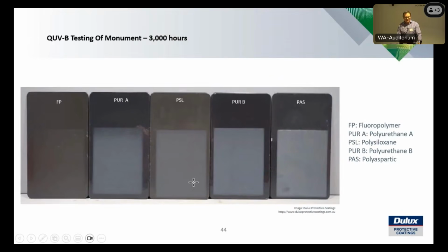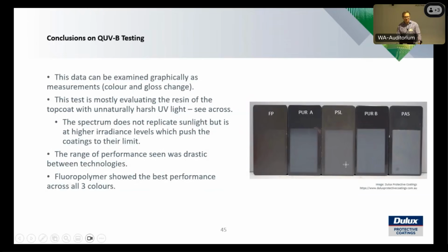And at 3,000 hours, the Colorbond Monument looks like Colorbond off-white in some instances there. And the fluoropolymer, there is some change there after 3,000 hours. So the conclusions of the QUVB testing: like I say, evaluating the resin of the top coat also under harsh UV light. It doesn't replicate sunlight, but it's a higher level of UV which gets pushed. The coatings are really pushed to their limit, but it's good to be able to find out what they can do.